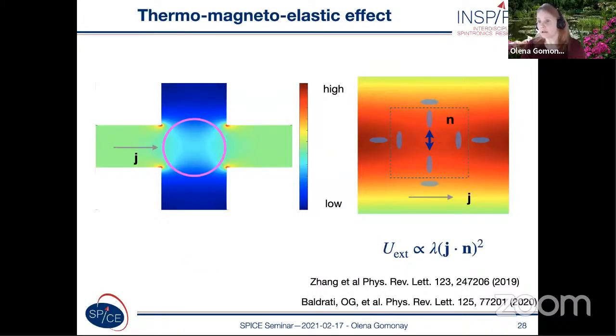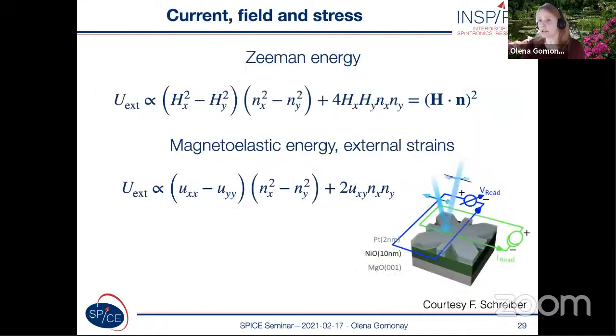This axis of elongation has a different direction on both sides of the interfaces, but if we sum up all the contributions inside the center of the cross, we find out that the average strain in this region has a preferable direction, vertical in this slide, and this preferable direction of striction through the magnetoelastic mechanism sets a preferable direction of the Néel vector. So we can conclude that such a thermomagnetoelastic mechanism can choose this or that orientation of the Néel vector locally and induce switching. And if we look at the formula and compare the magnetoelastic contribution with Zeeman energy, we see many similarities, but magnetoelasticity gives much more possibilities because we can vary sign, we can make it inhomogeneous, and so on.